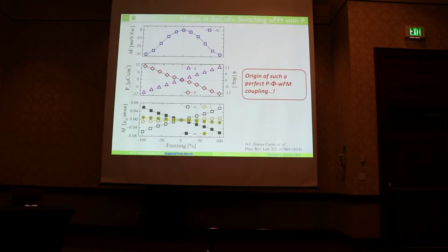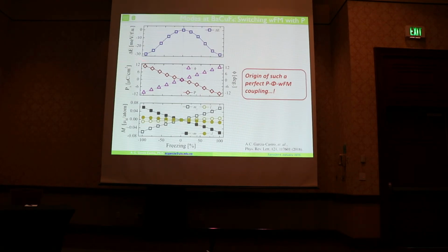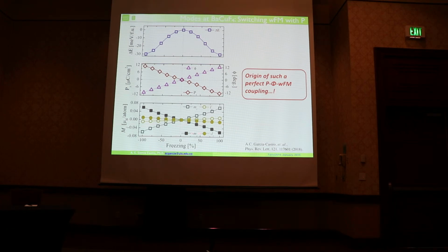Okay? So what we did next is to check more carefully what happened when we switch the polarization, okay? So first, we look very carefully here. Oh, I forgot to mention, of course, that in these ones, the difference in energy corresponds to the ground state as reported experimentally and as we already observed, okay? So when we look, for example, at the typical double well, what we observe is that when we condense the single polar mode from minus 100% to 100%, we have a classical double well shape when we look at the difference in the energy with respect to the high symmetry structure.